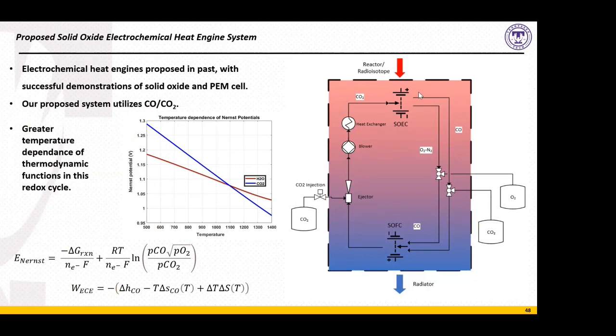And the final system that we want to lay out here, and this is a proposed future system that again would utilize solid oxide electrochemical cells, would be a heat engine operation. So the working principle behind this is you have a solid oxide electrolytic cell, which is sitting at a high temperature, which is receiving heat from some type of high quality heat source, be it a nuclear reactor or a radioisotope source. And then you have an SOFC at the lower end of a temperature gradient on the system. And just by flowing gases around in a closed loop, you can get out net work from the system.